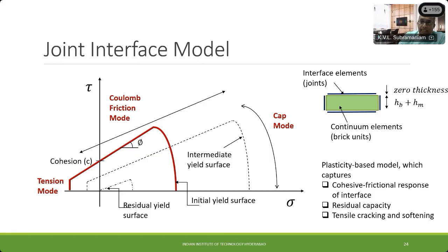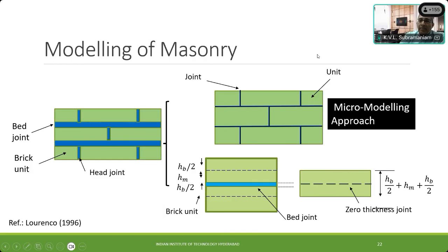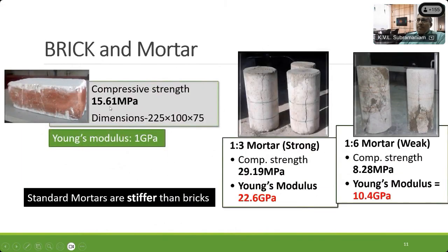And we're building houses with it. What's worse is we're building load-bearing structures. Here the compressive strength of the brick was 15.6 MPa, which seems fairly good, right? But its Young's modulus is barely 1 GPa. And if you look at the mortar, the 1:6 mortar, which is 1 part cement to 6 parts sand, gave me a compressive strength of 8.3 MPa. So the mortar is actually weaker than the brick, but it is 10 times stiffer than the brick. Even for a weak mortar, this is the state.